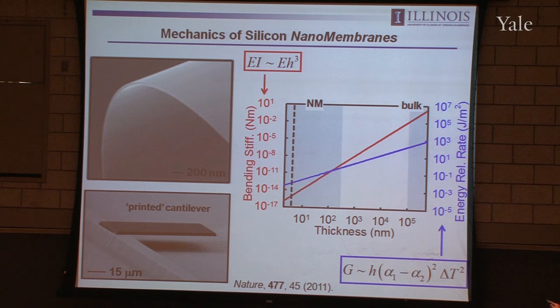And if you think about taking that silicon wafer and slicing it very, very, very thin, so take a silicon wafer and create from it a silicon nanomembrane, so a sheet of silicon where the thickness of that silicon might be 100 nanometers instead of 0.5 millimeter. What happens is, by shrinking the thickness, you decrease by many orders of magnitude the resistance to bending for an applied force, and that quantity is known as the bending stiffness. It's proportional to the Young's modulus, the intrinsic properties of the silicon, times the thickness of the silicon, whether it's the wafer or this nanomembrane, raised to the third power.